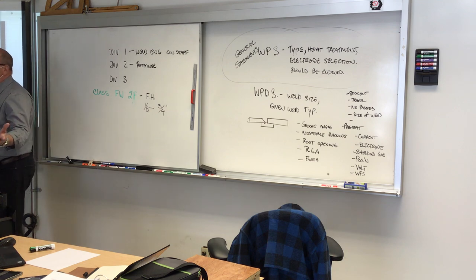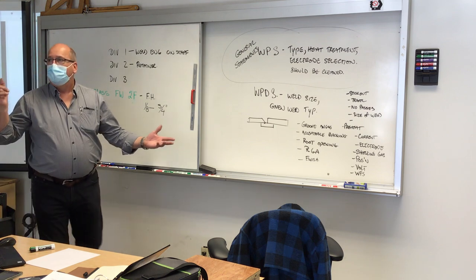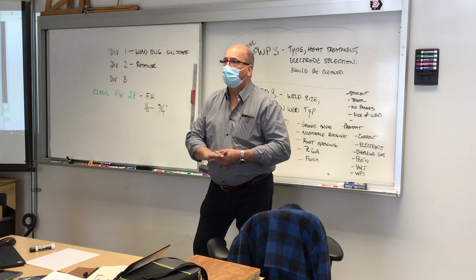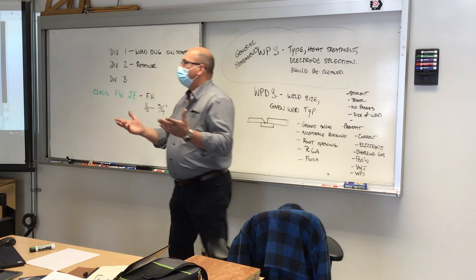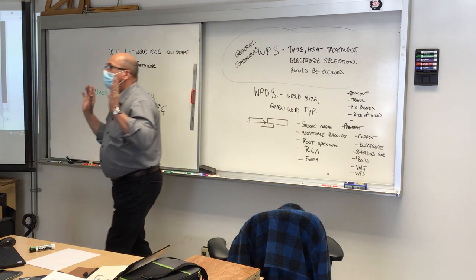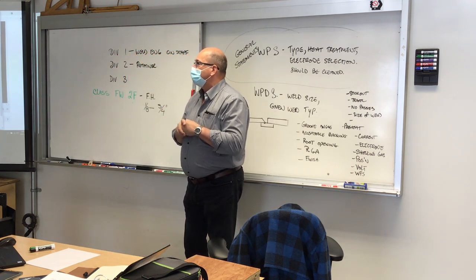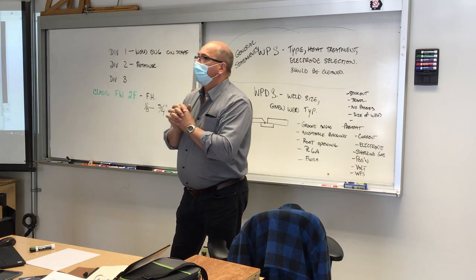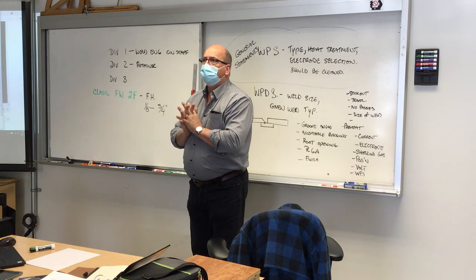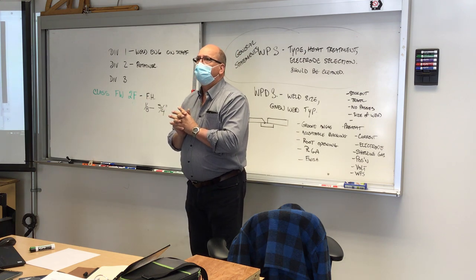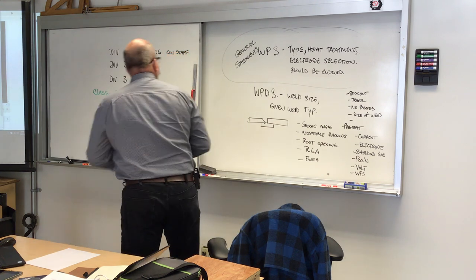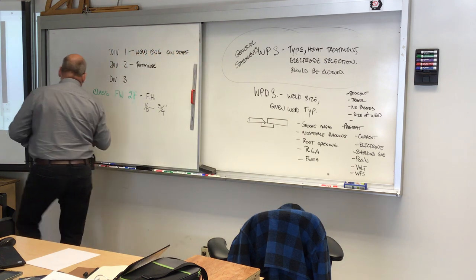What's the test? How do you test a tack? Snap it in half. It's destructive, we break it. What are we looking for? Pulling parent metal. We're trying to get parent metal ripped out, absolutely. Scott, what else are you looking for? Penetration. Okay, so what's unique about that penetration? I want to make sure it's taking off the sharp edge of the blade so it's actually in the root. Right. And it's got to be consistent. I think that's the key.